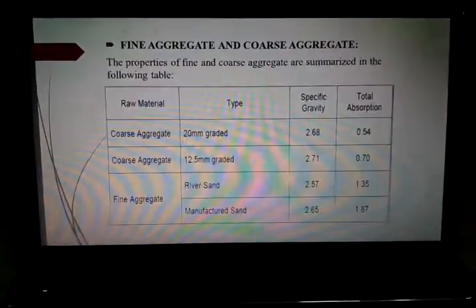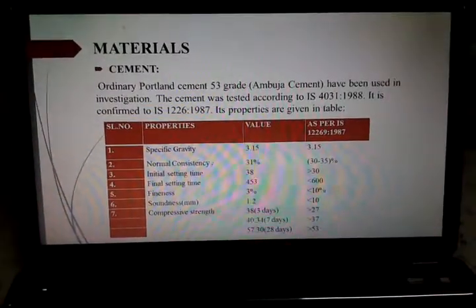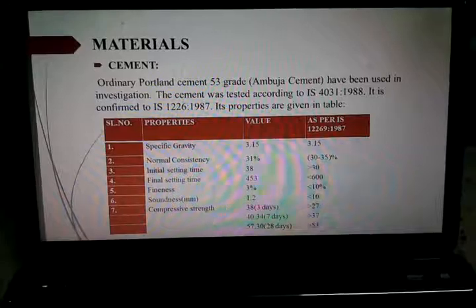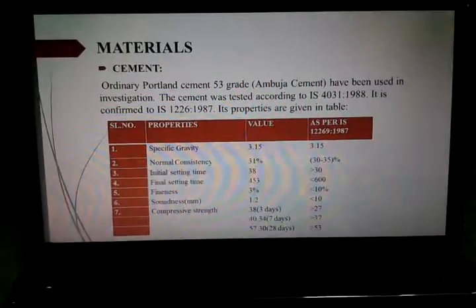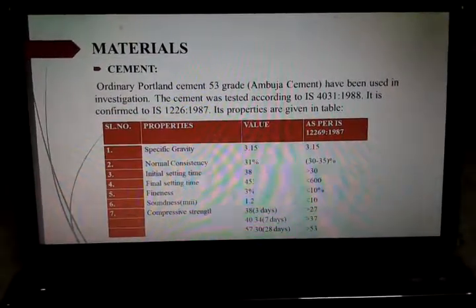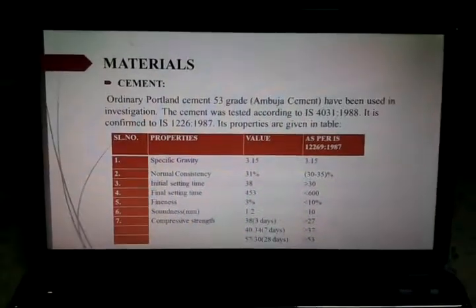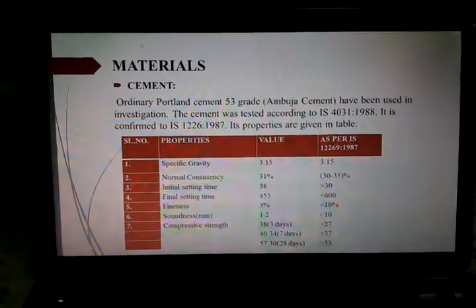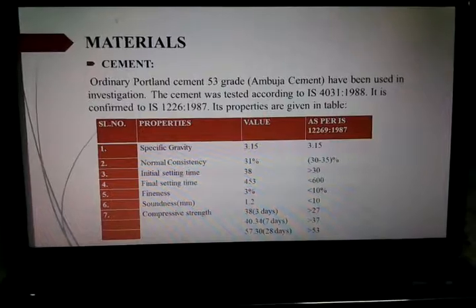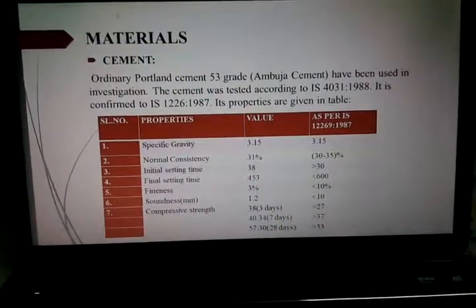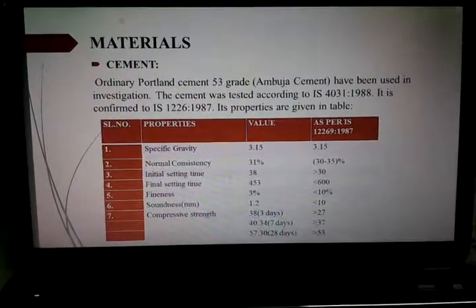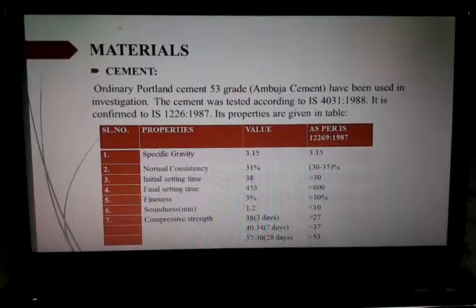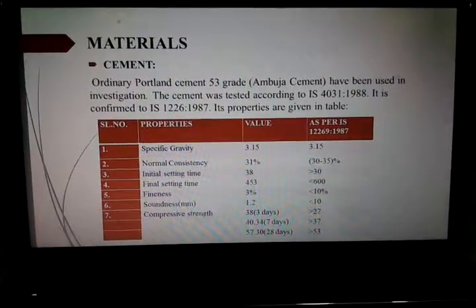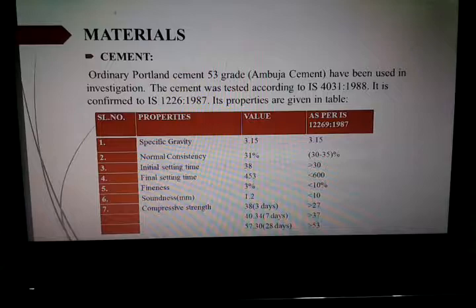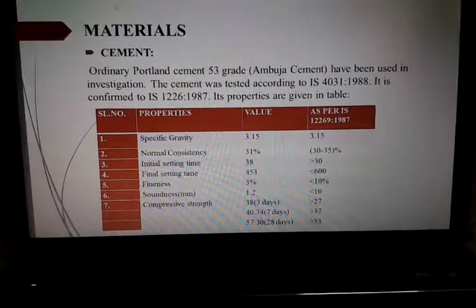Materials: cement. Ordinary Portland cement of grade 53 is used. The cement was tested according to IS 4031 1988. It conforms to IS 1226 1987. Its properties are as tabulated. Specific gravity is 3.15. Normal consistency is 31%. Initial setting time is found to be 38 minutes. Final setting time is 453 minutes. Fineness is 3%. Soundness is 1.2. And it is found the values are as per IS